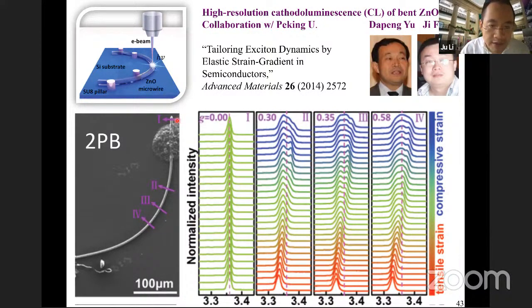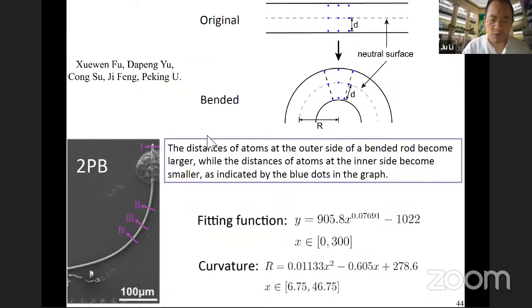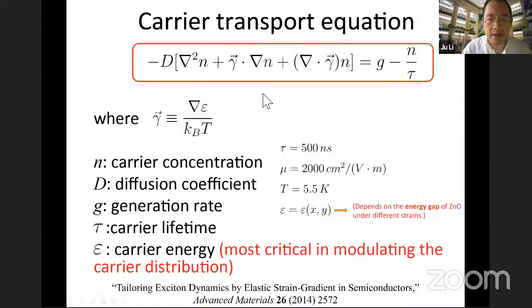What they found was that in this region, where there is no bending moment, doesn't matter where you excite the zinc oxide, the color of the light is monochromatic. But in this middle region too, when they scan on the tensile side, the color is this monochromatic red light. But as they scan towards the compressive side, there is a blue shift of the light. And depending on where the electron beam scans, the color of the light shifts. And so we fitted the profile of this microwire. We did some DFT calculations, and we wrote down this transport equation where this n is not electron density. This is the charge neutral electron hole pair density, the exciton density.